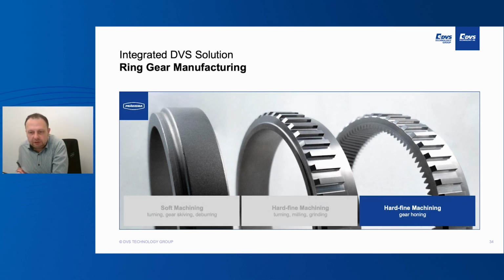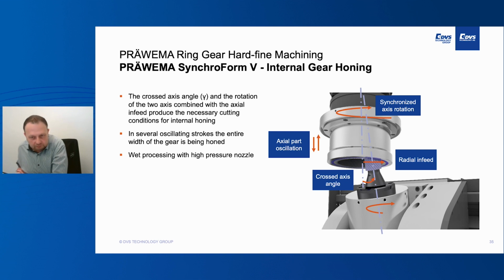After this grinding operation, the part goes through the hard fine machining of the gear. This is done by internal gear honing, and the internal gear honing uses a similar system to the skiving and the same system as the external gear honing. We need an X cross between the two axes, the axis of the workpiece and the axis of the tool. And then we also need the synchronization from NC. We have a radial feed rate and a small oscillation, and it takes around 60 seconds to clean up the part and do all the corrections which are necessary and required for the final part quality.